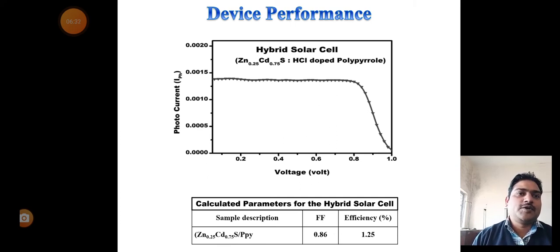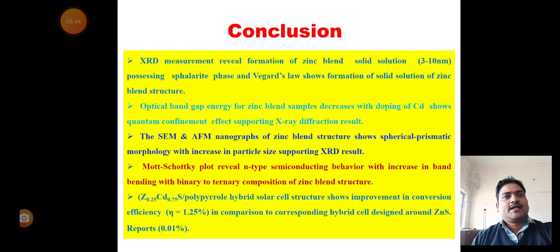The efficiency obtained for the hybrid solar cell based on zinc cadmium sulfide and HCl doped polypyrrole is 1.25 and fill factor obtained is 0.86. The conclusion of my work is that XRD measurement revealed formation of zinc blende solid solution of 3 to 10 nanometer, possessing sphalerite phase, and Vegard's law shows formation of solid solution of zinc blende structure.